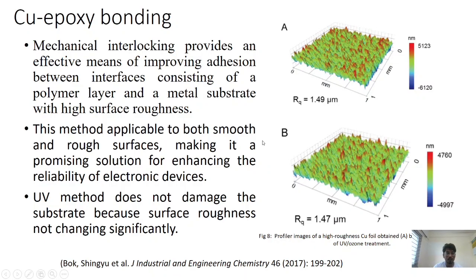Copper epoxy bonding is done by the adhesion process. Improving the interfacial adhesion between the metal or copper substrate and the epoxy is very important for reliable electronic devices, because if the proper adhesion strength is not there, this may cause delamination. Delamination means the separation of the copper and the epoxy resin. This causes the failure of the electronic devices.